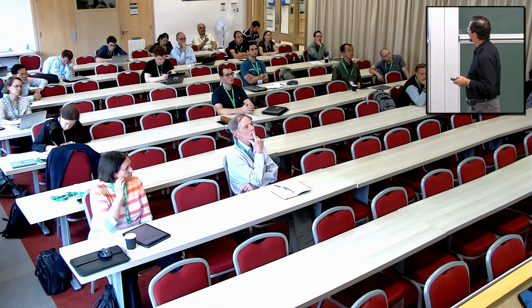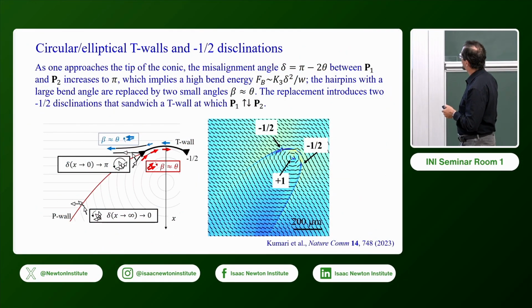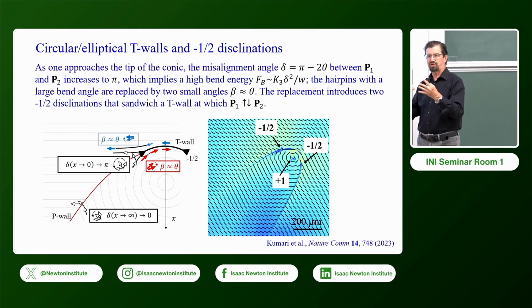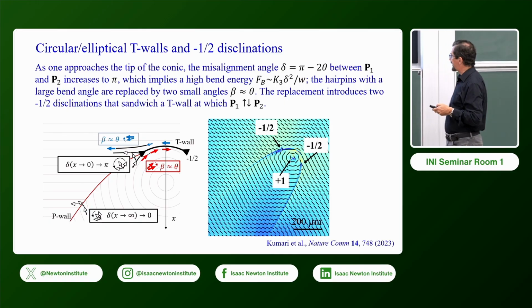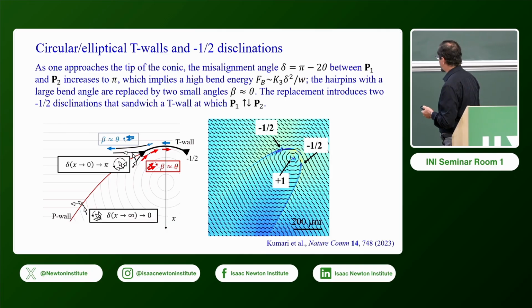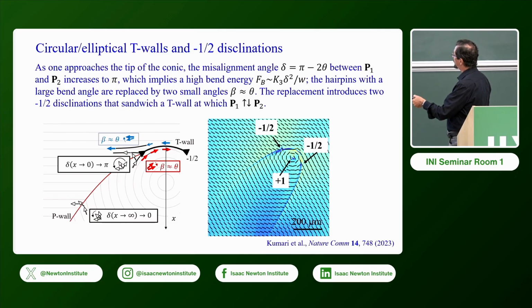So you mentioned the two minus halves, and then there's the domain wall. So yeah, let's see that. The domain wall is this. This is where we see relatively sharp realignment of polarization. It's not the mathematical cusp, but it's where the circular domain meets the more or less uniform domain. So you have the polarization that is realigning relatively quickly, shown here.